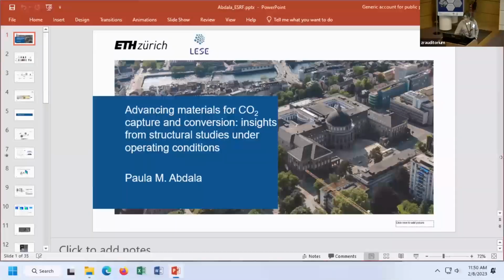Thanks. Yes, I agree. If we only had the EXAFS data, I wouldn't be certain that this was due to amorphization. So for me, this is why the combination of techniques becomes more powerful than each of them alone. We did different modeling: with fixed coordination number and free Debye-Waller factor, and then fixed Debye-Waller factor with free coordination number, and it was way better with the free coordination number. Then you can free both of them, but then you get huge errors. So if we stick to one model, you can consider the disorder isotropic and fix the Debye-Waller factor. At the end, that's what we did, but we tried all. Thank you for your question.